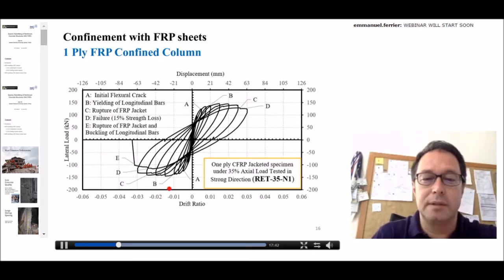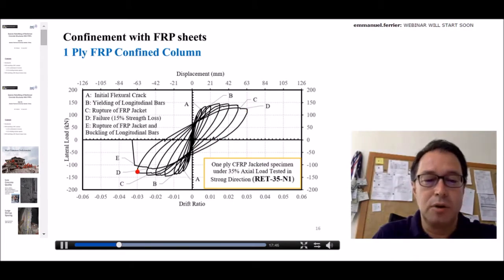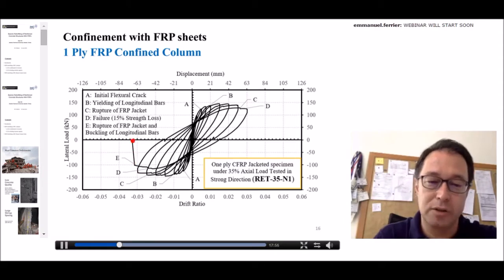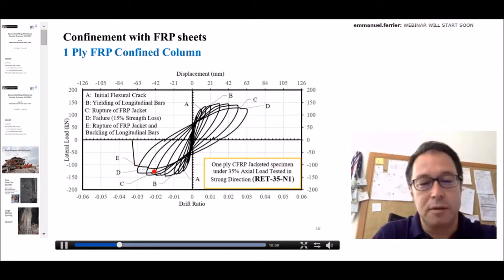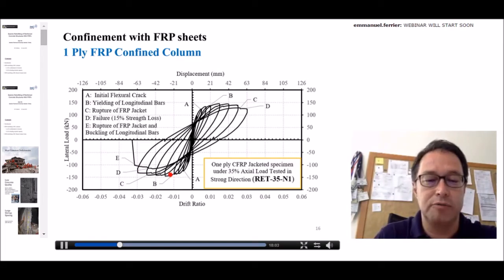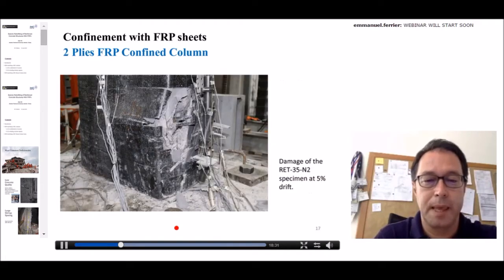So if you look at the load displacement diagram, which is obviously better than the reference specimen, you see we could go up to 3% drift, where rupture of FRPs was observed. And of course, upon rupture of the FRP jacket, the strength is lost again quite suddenly. But you can notice that we didn't experience strength degradation at around 1% drift, even at 2%. Failure was just around 3% drift ratio. So obviously we had much better performance. The energy dissipation capacity is much better, which means that this retrofitted column could survive the same earthquake, or could perform much better even in a stronger earthquake.